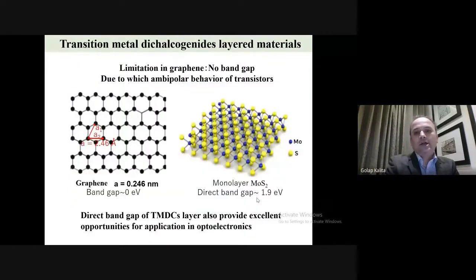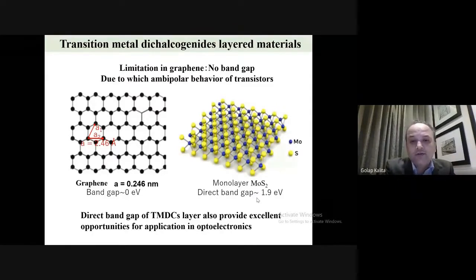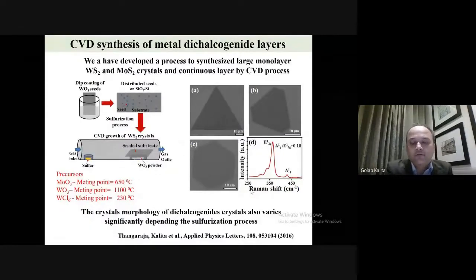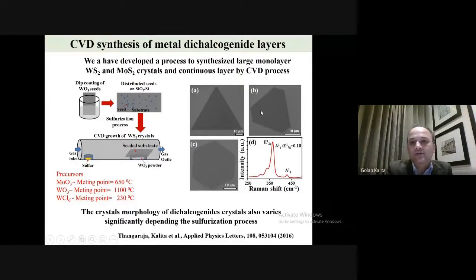Then about MoS2 growth, or chalcogenide growth. In the case of chalcogenide, as I discussed before, a monolayer of MoS2 has one molybdenum atom in the middle, and in the top and bottom you have two sulfur atoms. So it forms MoS2 layers. For the growth process, we use MoO3, or for WS2 growth, WO3 or chloride. We get very nice crystals. We can grow triangular crystals, truncated crystals, or hexagonal crystals.